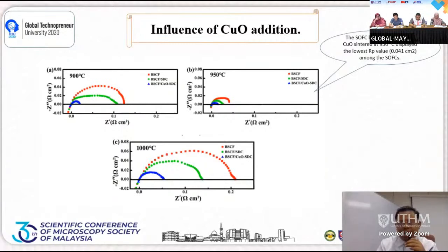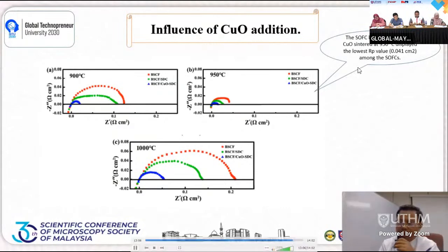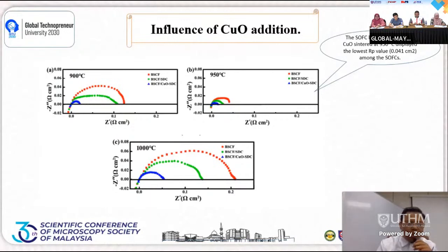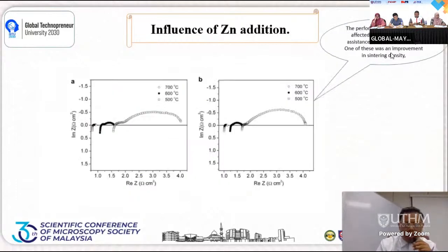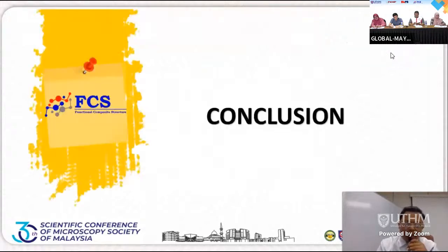highest is at 950 degrees, which is the impedance at 950, and it shows the lowest RP value, which is 0.041 ohm centimeters squared among the three different temperatures. And then last one is for the influence of zinc addition. The performance of the cell was affected by zinc sintering assistant in two different ways. One was improvement of sintering density. It showed a very good feedback with zinc addition.